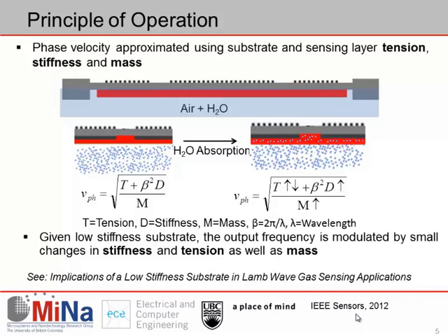In common FPW or SAW sensors, or acoustic sensors like some of those we saw today, the substrate is so stiff that if the sensing layer is a polymer, any changes in that sensing layer related to stiffness or tension go undetected. That is, the frequency associated with these changes is completely washed out by any frequency change associated with the stiffness of the piezoelectric material. Given that we have fabricated a low stiffness substrate, the output frequency can be modulated by small changes in stiffness in the sensing layer and changes in tension in the sensing layer, as well as mass. For a further theoretical description of this, please see Christoph Sielmann's work in the proceedings, Implications of a Low Stiffness Substrate in Lamb Wave Gas Applications, or check out his presentation yesterday.